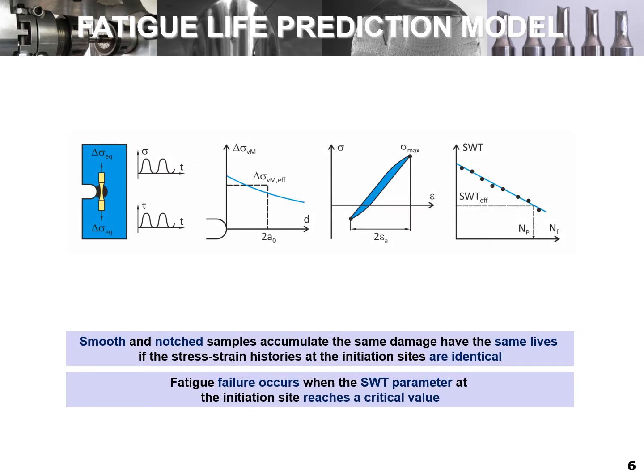The predictive model is based on two premises. One, smooth and notched samples accumulate the same damage and have the same lives if the stress-strain histories at the initiation sites are identical. And two, fatigue failure occurs when the SWT damage parameter at the initiation site reaches a critical value. The modus operandi consists of calculating an effective value of von Mises stress range at the critical region by applying the theory of critical distances, which is used to estimate a corresponding value of the SWT damage parameter, enabling the calculation of crack initiation life using the fatigue damage law developed in the previous stage.